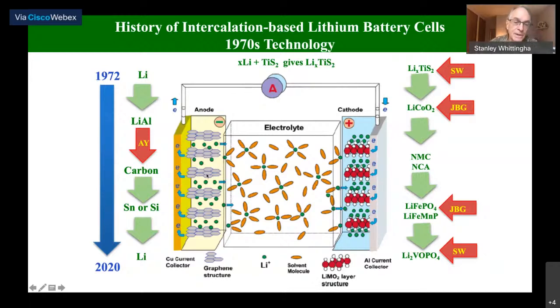The issue here is the graphite takes up half the volume of the cell, and you need 72 grams of graphite to store 7 grams of lithium. So it's not all that efficient from an energy density point of view. So present researchers are now working on tin or silicon substitutes where we can store up to 4 lithiums per silicon or tin. And again, the holy grail is really to go back to lithium metal if we can make it safe. On the cathode side, we started with lithium titanium disulfide.